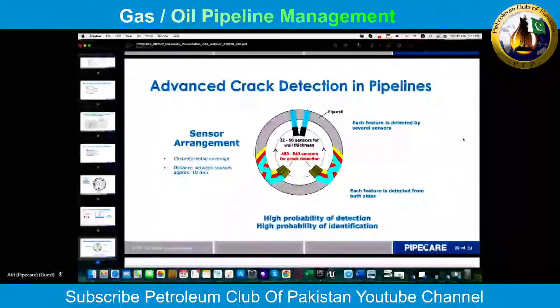The industry has moved from giving the depth of cracks in bands, which was in the past, where we had bands 0 to 1, 1 to 2, 2 to 4, or larger than 4 millimeters. We are now giving distinct sizes of the crack depth, which has an impact on the crack assessments, because when bands were given, always the worst case had to be taken. So even if a crack was 2.1 millimeter, for the assessment, because the bandwidth was from 2 to 4, the assessment always used the worst case, meaning 4 millimeters.